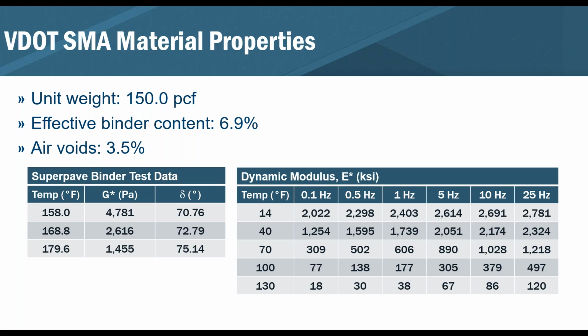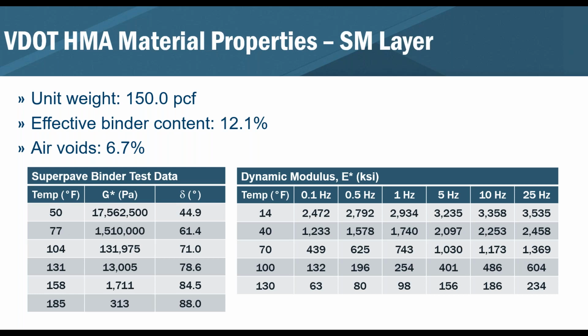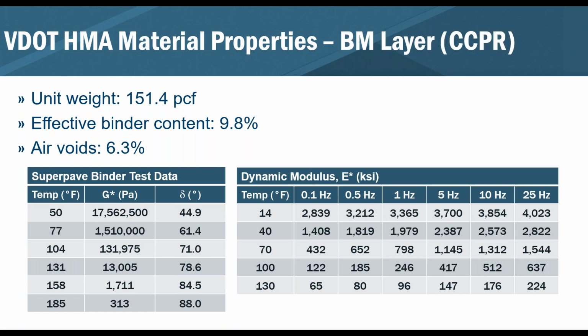Similar on the surface mix layer. Again, we've got pretty good values there: 12% binder content, 6.7% air voids, and then obviously the binder test and the dynamic modulus test results. Then on the CCPR layer, same thing here. Now the effective binder content drops down to 9.8 with the air voids at 6.3. The dynamic modulus itself is still looking relatively good compared to the other two as well.